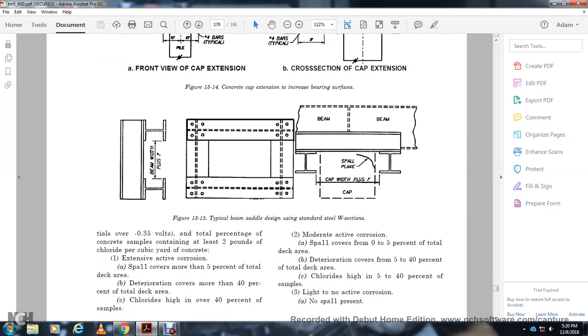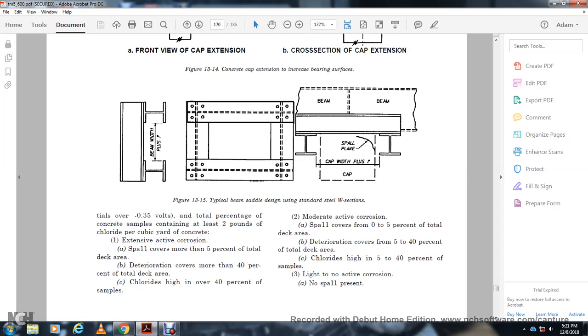potential over negative 35 hundredths of a volt, with the top total percentage of the concrete samples that contained at least 2 pounds of chloride per cubic yard of concrete. Extensive active corrosion, spall: cover 5%, total deterioration covers 40% of the total deck area, chloride higher in over 40% of the samples. The moderate active corrosion spall covers 0 to 5% of the total deck area, the deterioration covers 5 to 40% of the total deck area. Chloride is high in 5 to 40% of the samples. The light: no active corrosion, no spall present.